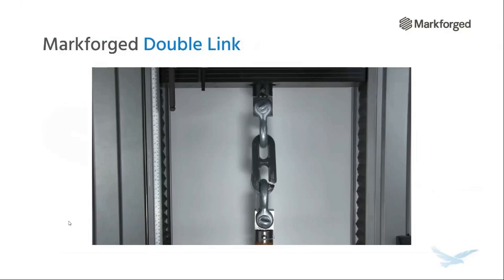So going back to that mechanical flexural stress and strain chart, remember we saw that carbon fiber reaches its maximum strength and there's not much stretch before breakage, and that's exactly what we saw here. And you can see some of those fibers that end up protruding through the part. You can see some of those fiber strands as they were ripped apart. But again, this part was loaded so that those fibers are in tension.